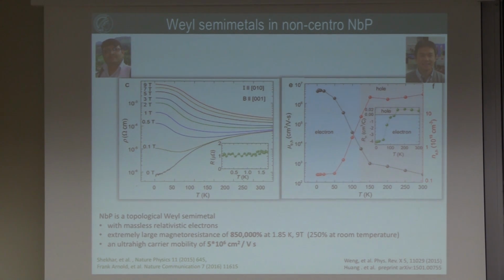So we did transport measurements on niobium phosphide, which was our most favorite material, different than other people, and very typical for all these materials, and this reminds very much also of graphene and bismuth: we have a very low resistivity and very good RRR values in all this material, which means the conductivity at room temperature is much lower than at low temperatures.